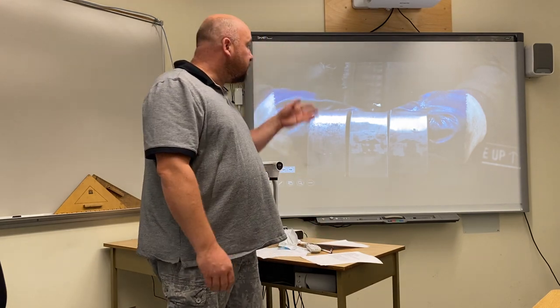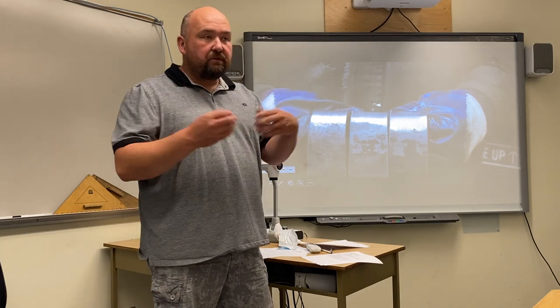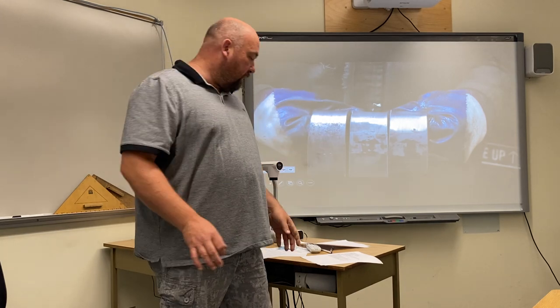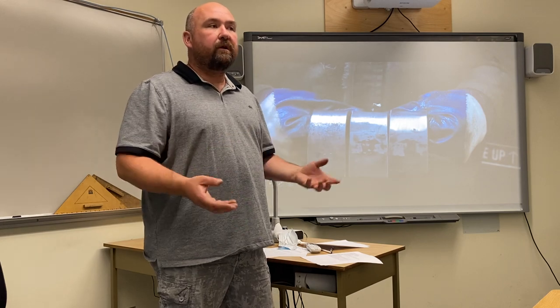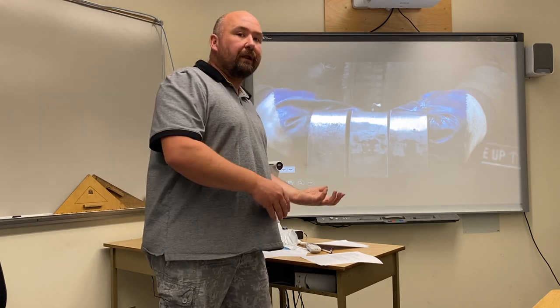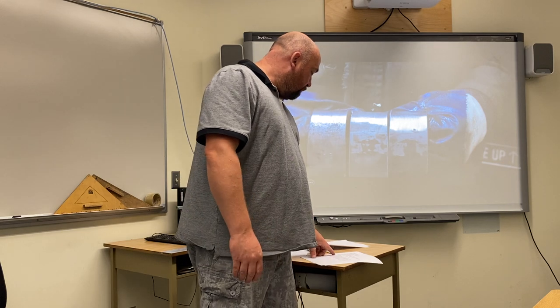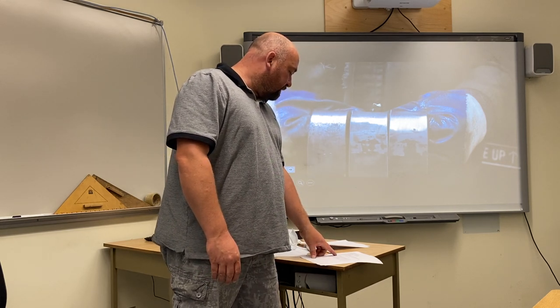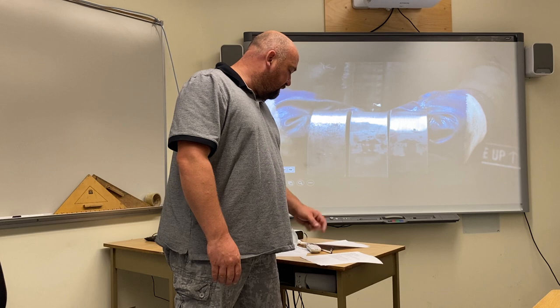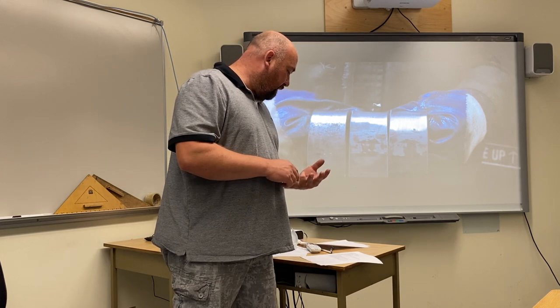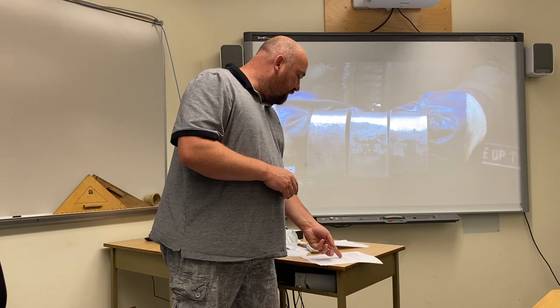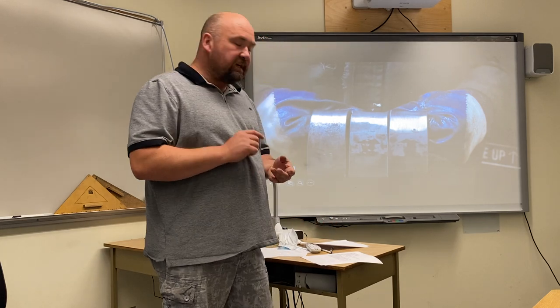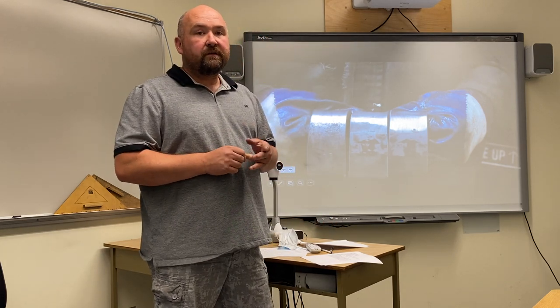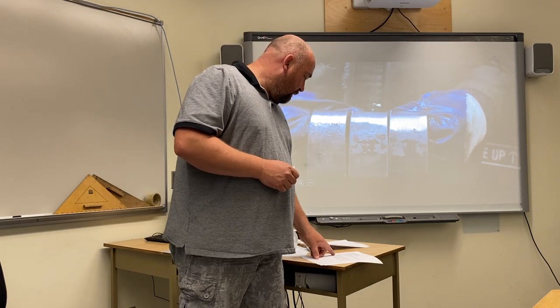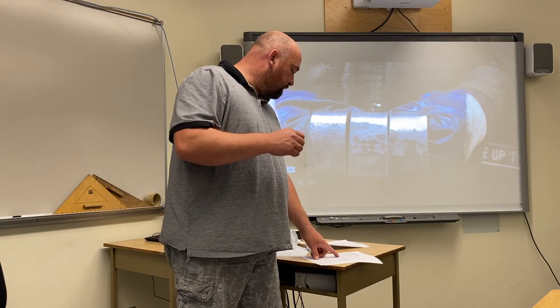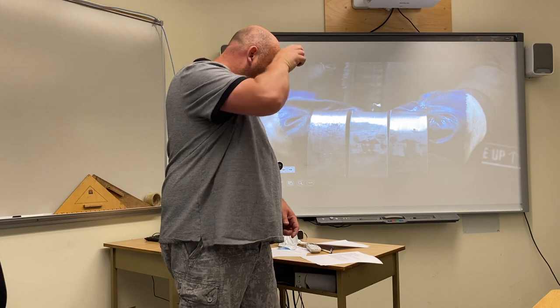Your limit of your flaw is, like I was saying, when you bent your plates and say you do have some porosity clusters. Okay, there are rules built into the code for what they're allowed to fail you on, what they're allowed to pass you on. Okay, the limits of flaws, so porosity or fusion defects such as slag, lack of fusion, inadequate penetration, the maximum deviation of a single flaw is not to exceed 2.6 millimeters. Flaws of 2 millimeters to 2.6 millimeters are evaluated based on how close they are together.